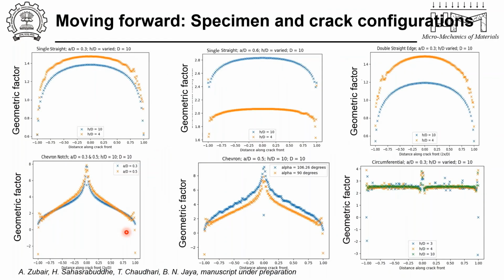Not going into the details, but there are some interesting results coming out of these calculations as well. In the single straight crack sample, you see that for the H/D of 4, you have a lower geometric factor as compared to H/D of 10. But for a double straight edge sample, it's going in the reverse direction. Whereas the aspect ratio doesn't seem to play so much of a role at all for the circumferential crack. This is expected, right? Because a circumferential crack does not result in bending of the sample because it's a symmetric crack. So for different H/Ds, the geometric factor remains the same. These are some of the things that we have evaluated.